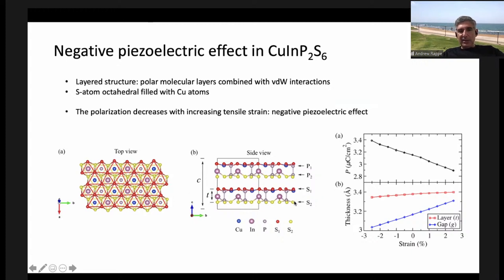Then in between the bread of the sandwich, there are three sites. And one of them is occupied by copper, indium, or a phosphorus dimer. And that repeats. And those are the three species that are shown here. And you can see in the side view, these phosphorus dimers are vertical. And the copper is way off center. That's the reason this thing is polar. And the indium is only a little bit off center, and that doesn't matter that much.